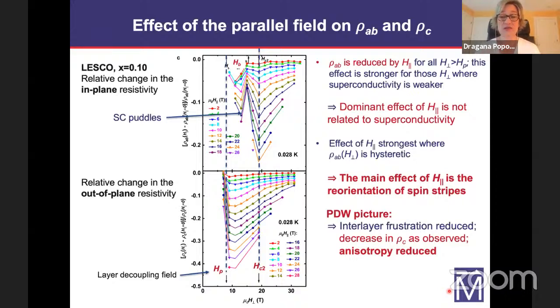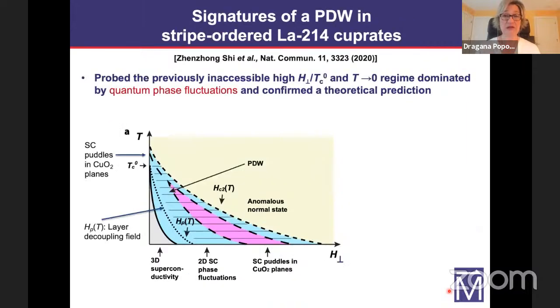And we see also qualitatively the same behavior on LNSCO. We have repeated this also at many different temperatures. And here again, I'm using the sketch to show you the range of parameters where we see the effect of parallel magnetic field, or the evidence for a pair density wave. So this is shown by this hatched region here.